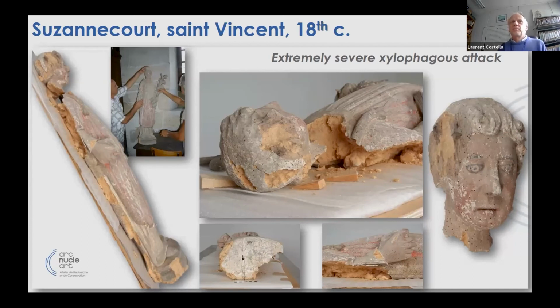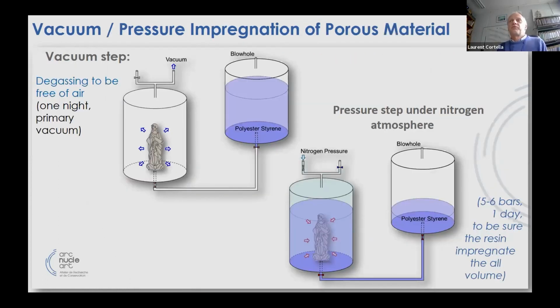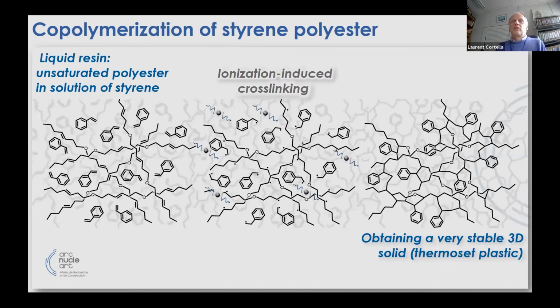The last example is completely different. It is the consolidation of a wooden sculpture with extremely severe xylophagous attack. So the idea of this kind of consolidation is first to make a vacuum-pressure impregnation of the porosity of the wood, by first degassing the porosity and then incorporating the resin and putting some pressure to have a good penetration of the whole volume. Then we trigger the cross-linking, the polymerization, with the gamma irradiation, obtaining a very stable 3D net in solid form, which is a thermoset plastic.